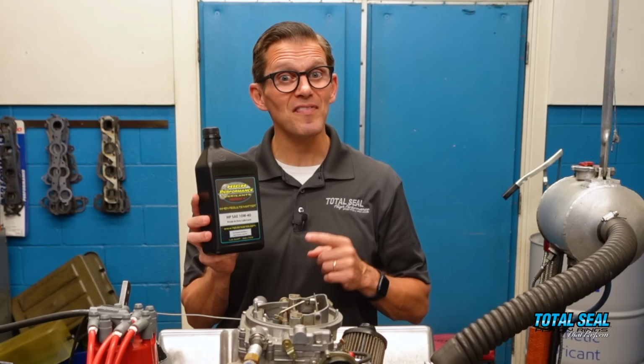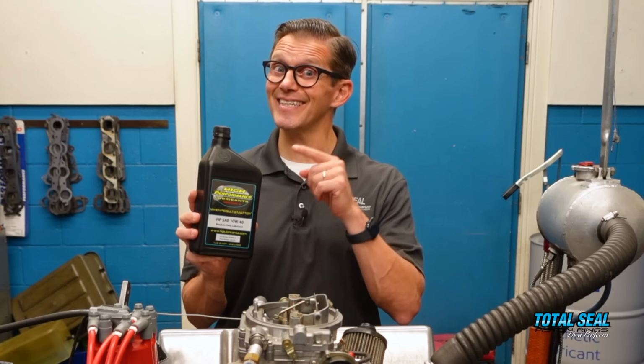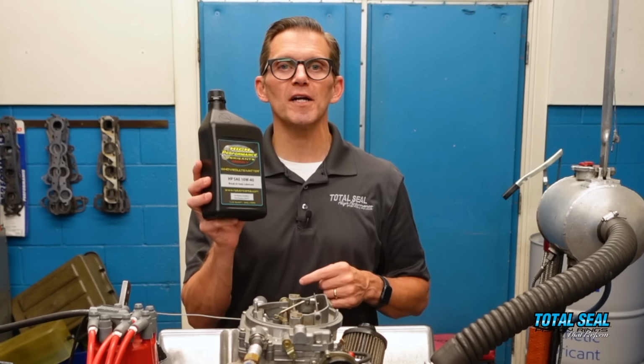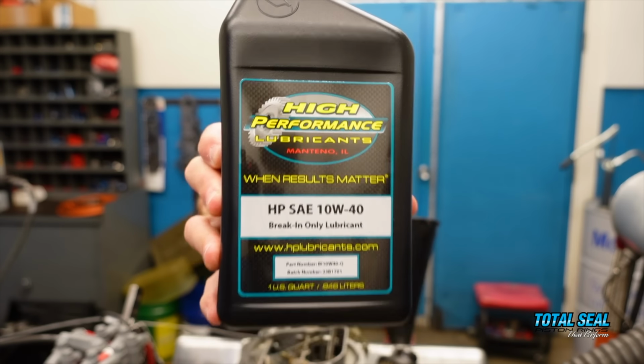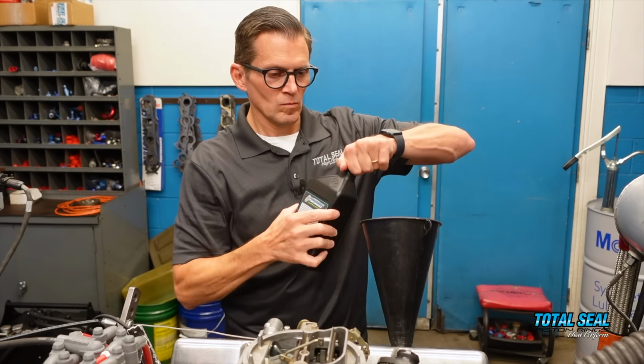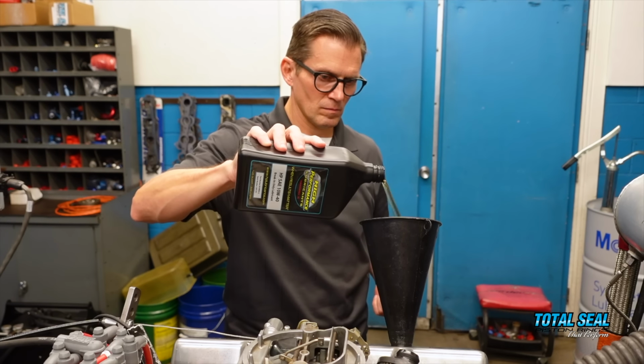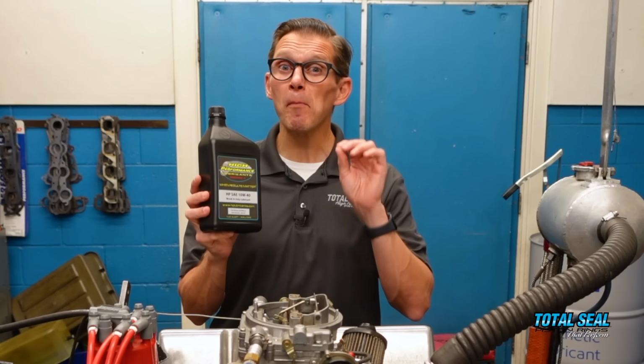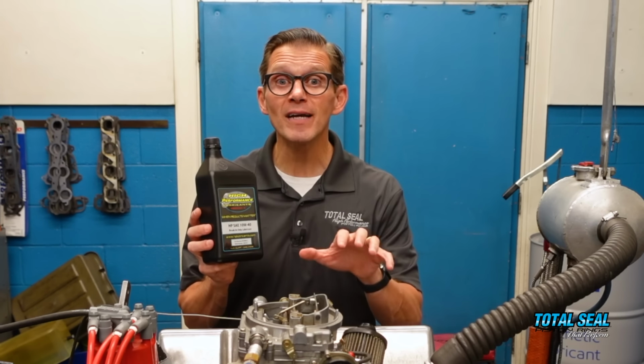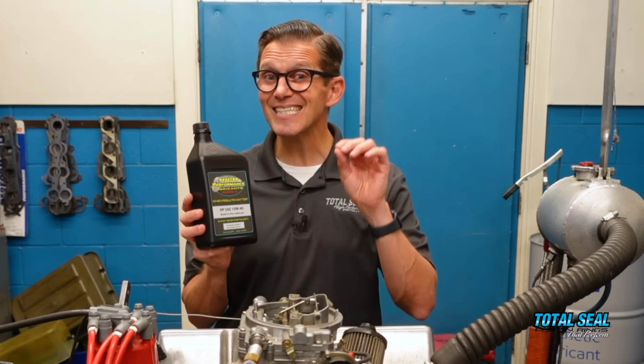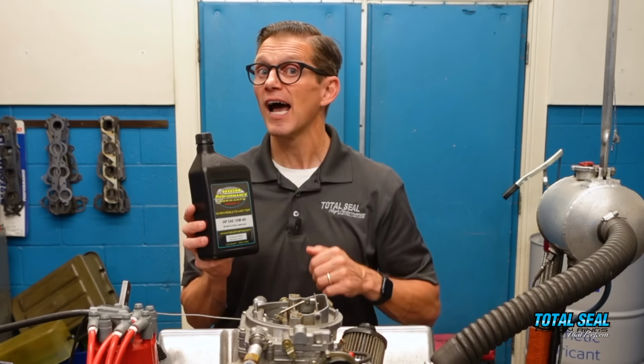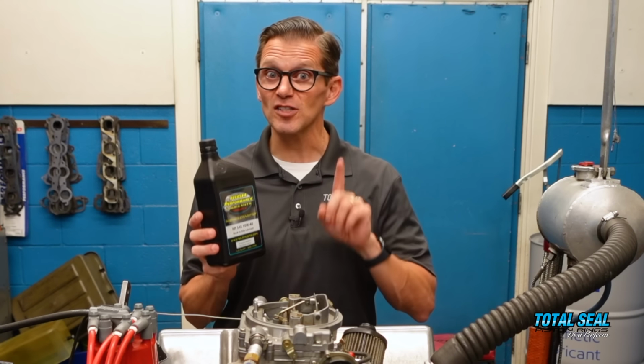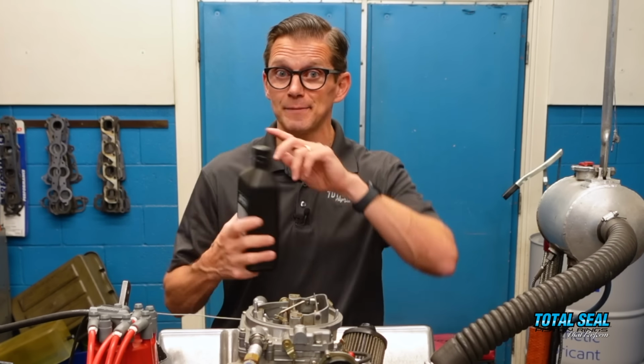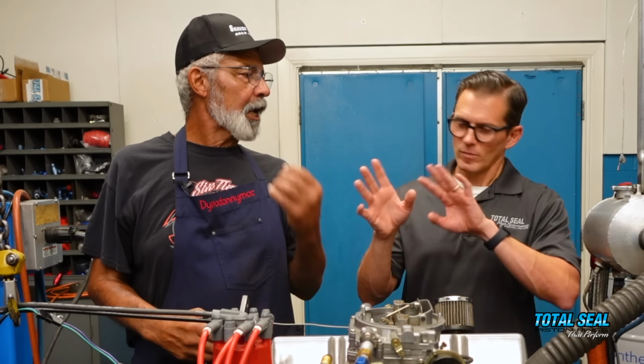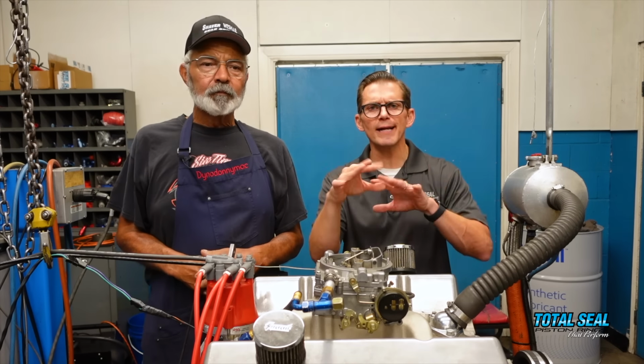Break-in oil isn't about the name that's on the label. It's what's inside the bottle that matters. We're going to use the break-in oil from High Performance Lubricants, not because it says it's break-in oil, but because it is higher zinc, lower detergent, which is perfect for breaking in this engine. Not only because it's a flat tappet camshaft engine, but that same balance of no friction modifiers, higher zinc, and lower detergent is also excellent for ring break-in. We even did a little flush before the runs. We always do that to make sure we're getting an accurate result, so any assembly debris is out of the way.